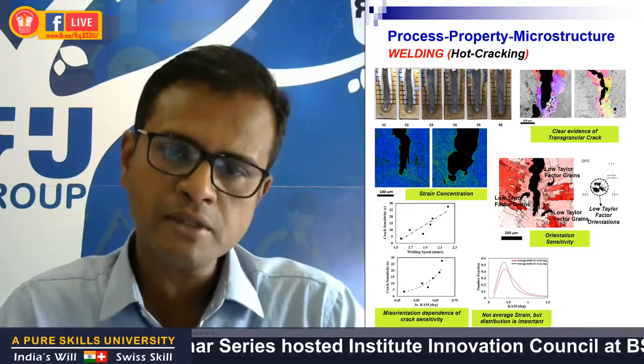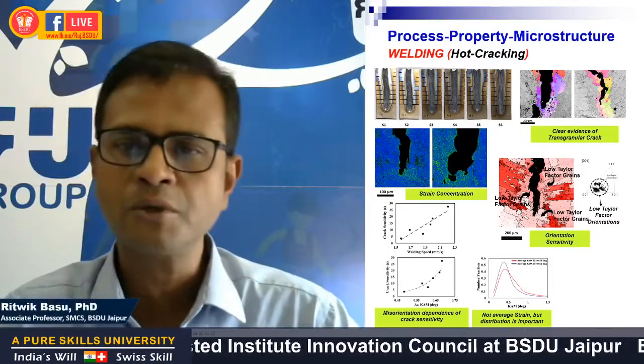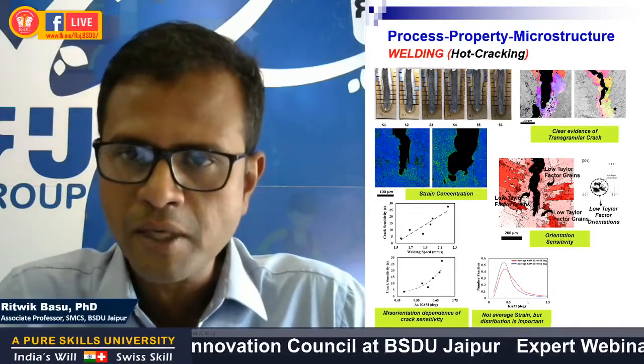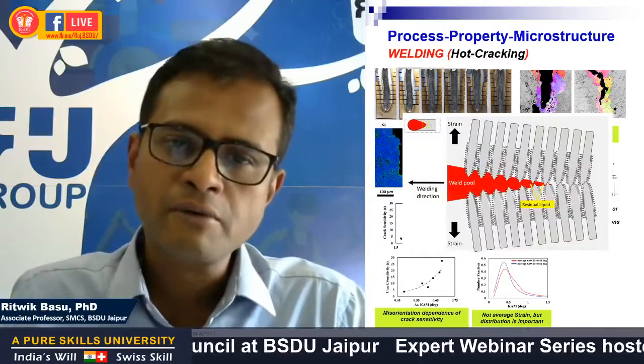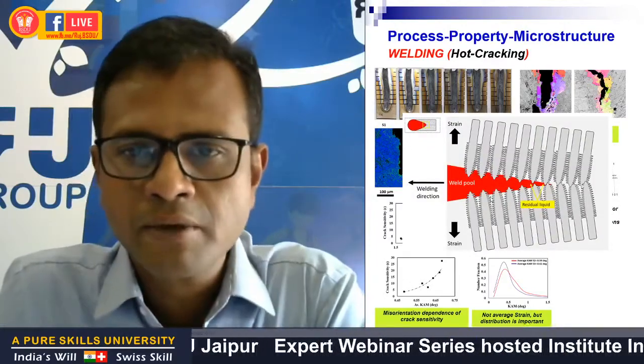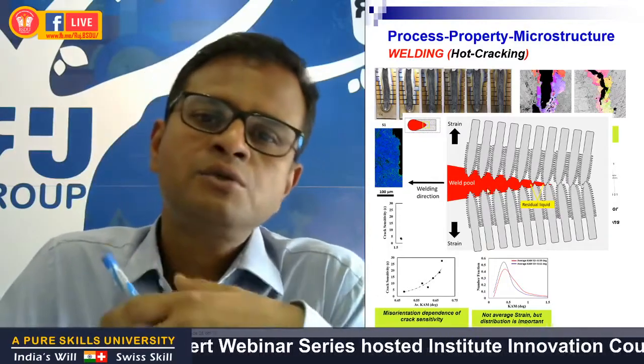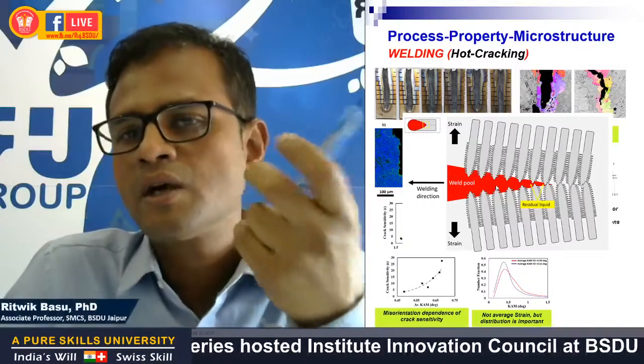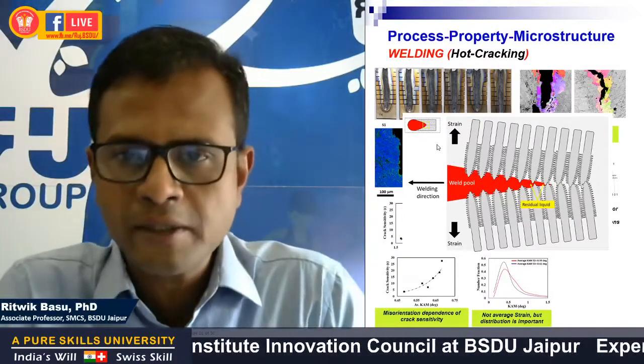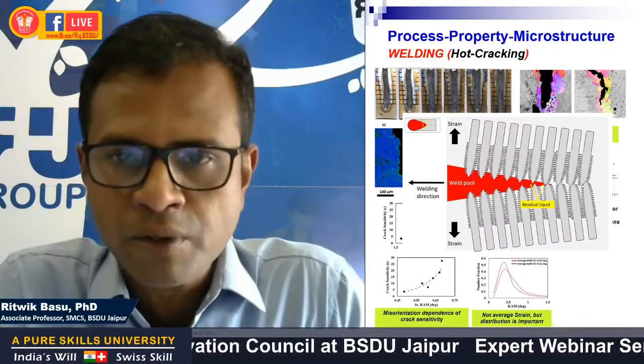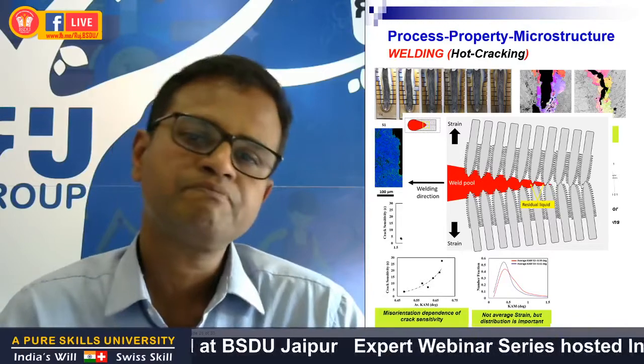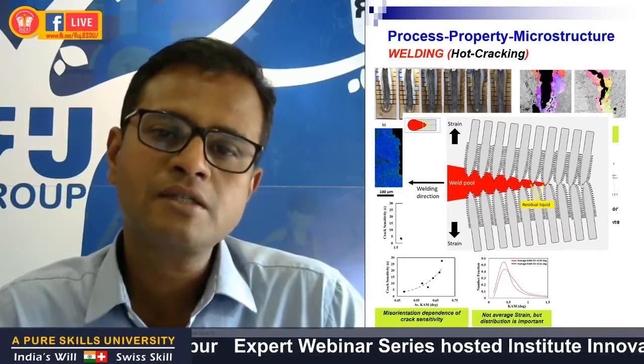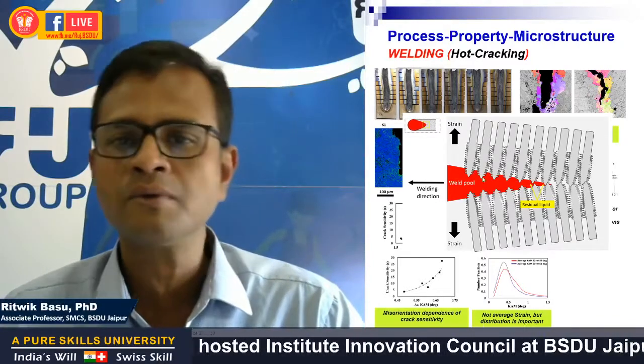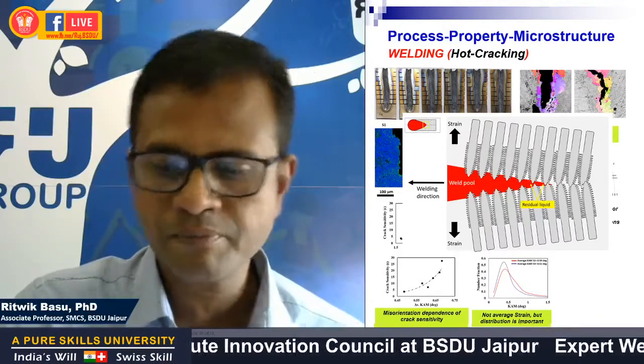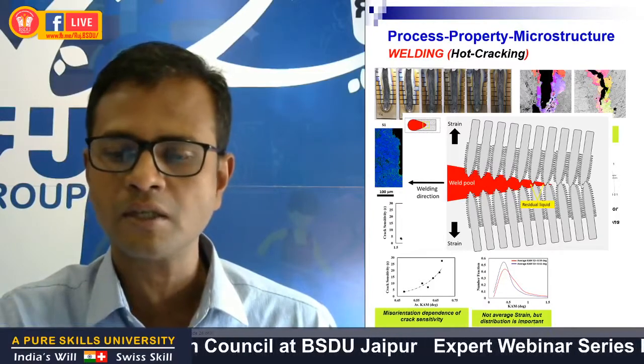So the primary reason for cracking could arise due to the thermal mismatch strains that develop during solidification of the residual liquid that is trapped between the interdendritic regions. So these cracks are usually seen to accumulate more at the higher welding speeds. However, for our samples, the samples that exhibited a low tendency to cracking possibly constituted a less stable liquid film. So with increase in the welding speed, the tendency towards forming a stable liquid film was more likely, and that increased the strain concentration around the liquid, leading to higher cracking tendency. So this is a work of another MTech student of mine, which is under communication.